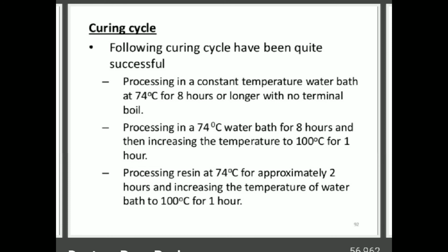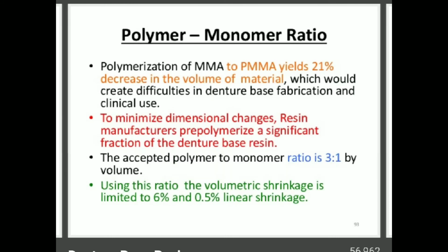Then about the curing cycle. There are three different curing cycles. One is processing in a constant temperature water bath at 74 degrees centigrade for 8 hours or longer with no terminal boiling point. Keep it at the temperature of 74 degrees centigrade for 8 hours, then do the curing. The other one is first you have to cure it at 74 degrees centigrade for 8 hours, then increase the temperature to 100 degrees centigrade for 1 hour. Then another one is 74 degrees centigrade for approximately 2 hours and then increase the temperature to 100 degrees centigrade for 1 hour. This is the fast curing cycle, right?